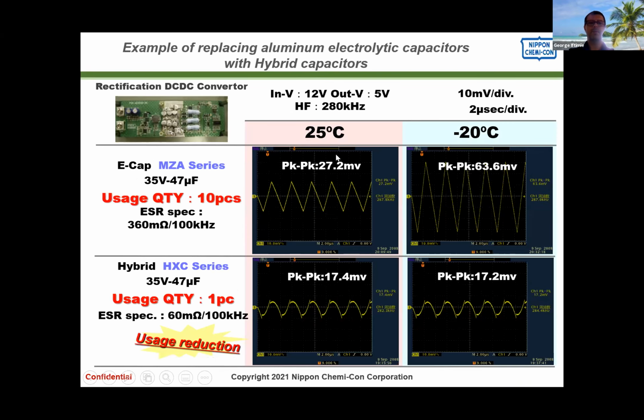This is another example, and one thing to see over here is, especially at minus 20 degrees C, the difference is significant. And one other thing that you see on the application itself, of course, is there is no difference in the peak voltage on the hybrid capacitor. It doesn't matter that it's 25 degrees or minus 20 degrees C, essentially you have the same exact behavior. But with a liquid part, you have significantly worse change. And that's before you even take into account the fact that you're only looking at 1 hybrid versus 10 electrolytic capacitors.